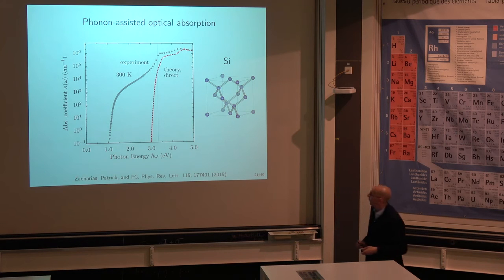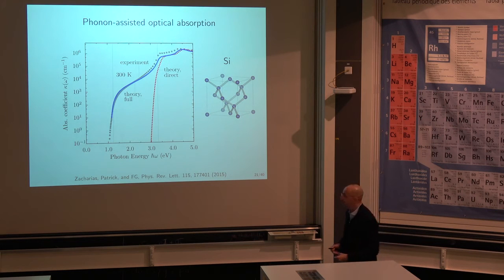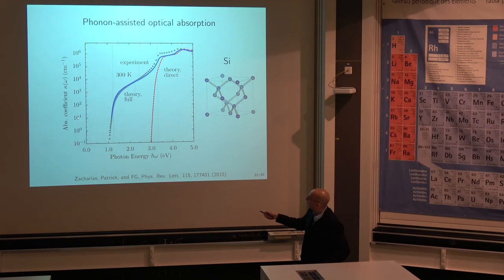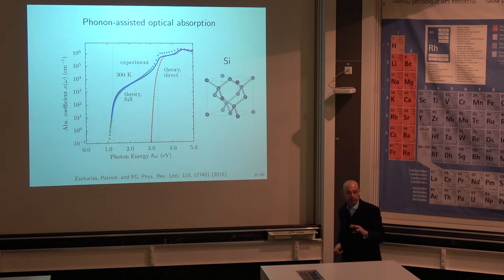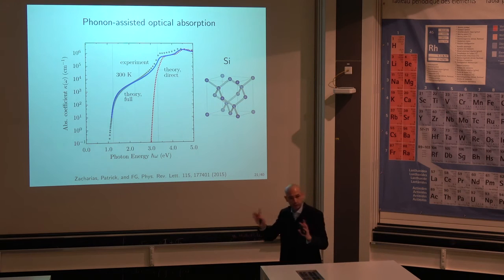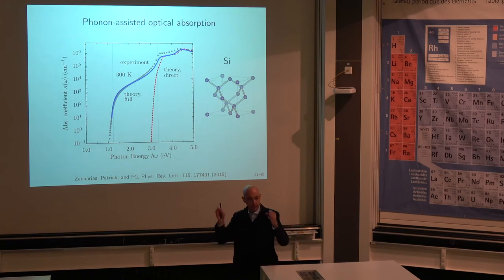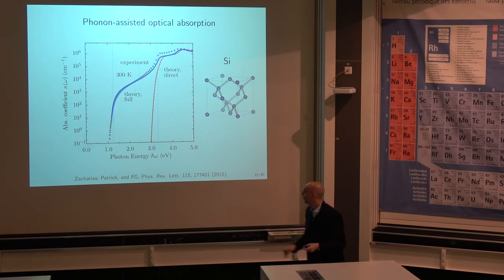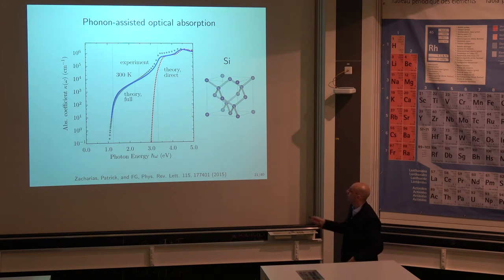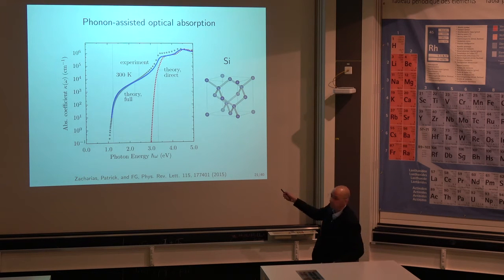Now, if you switch on electron-phonon interactions, you obtain the blue line, and you can see basically that there is an agreement which actually spans 5 orders of magnitude here. And let me say that in this curve, there is absolutely no fudge factor, so we're not changing things to make it look better. This is exactly how it comes out of the calculation without any modifications. So the only thing that doesn't work very well is that here we underestimate the absorption, but actually this has nothing to do with phonons.